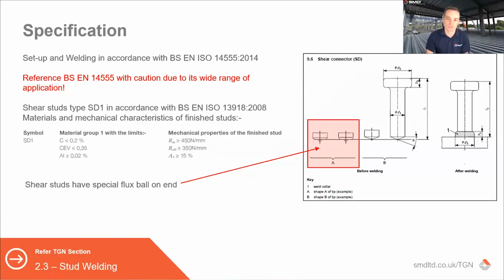So the specification of a shear stud, what shear studs are they, where do they come from, what do we use? The specification of shear studs, the product itself, is from BS EN ISO 13918. That's the image you see on the right hand side, and the studs that we use in terms of welding to steel are ones with a flux ball on the end. So you can see this A parameter here. The type is called an SD1 type, and then the welding of the studs is carried out in accordance with BS EN 14555.